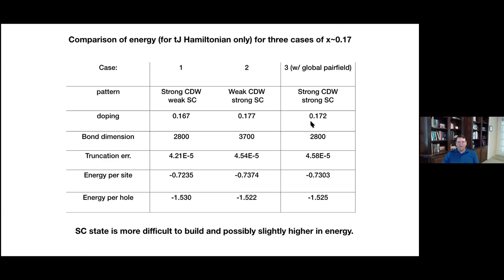Okay. So we can compare these states and try to see which one is the true ground state. The main conclusion is that they're so close, we can't resolve them too well. Here's the bond dimension, the truncation error that we got for each of these states, the energy per site. But another way of looking at the energy: the biggest change in the energy can come from just how much doping you actually got. So you can look at the energy per hole, where you subtract off an antiferromagnetic background, and that gives another way to compare it. Essentially these things are nearly degenerate.